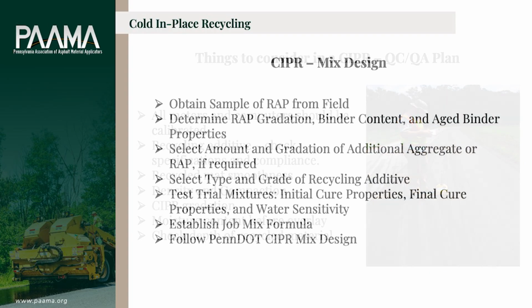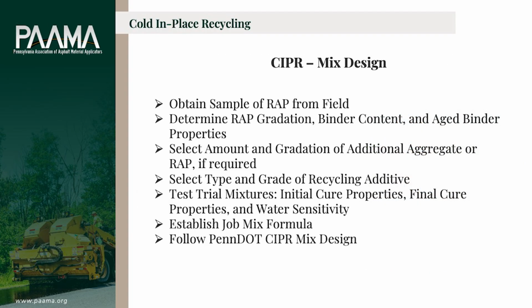The mix design, okay? We already got samples from the core samples in the field, determine the gradation and the binder content, select the amount and gradation. You know, there might be some additional asphalt within those mixes, especially if there's a lot of chip seals that we can use. The residual asphalt properties can help in the mix design and cut down on the amount of emulsions that need to be added in the mix.